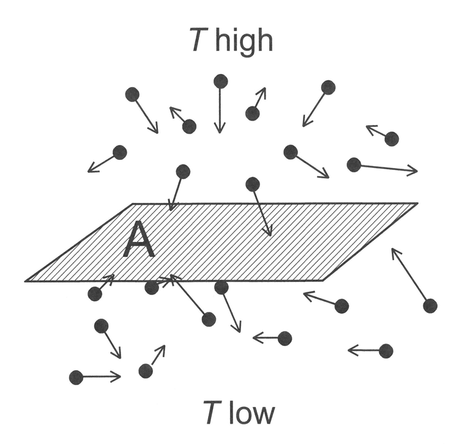For a U process to occur, the decaying phonon has to have a wave vector q₁ that is roughly half of the diameter of the Brillouin zone, because otherwise quasi-momentum would not be conserved. Therefore, these phonons have to possess energy of k θ/2, which is a significant fraction of the Debye energy that is needed to generate new phonons.